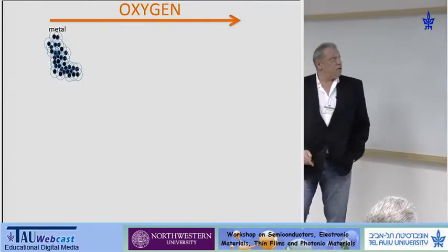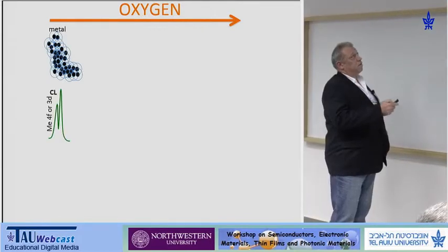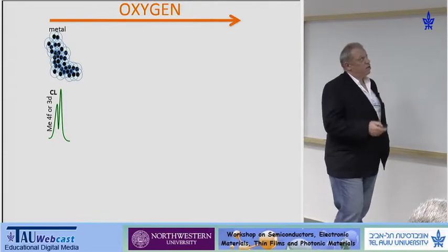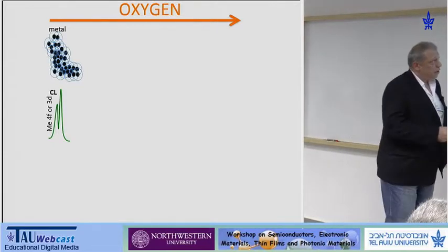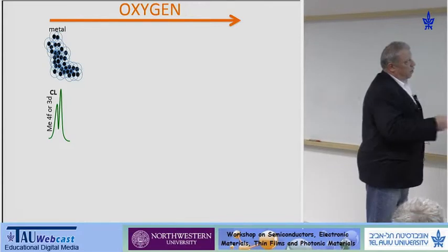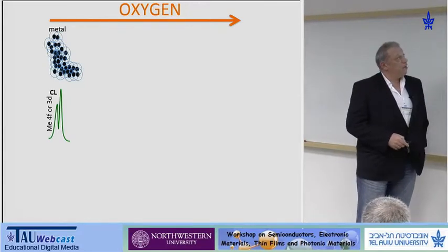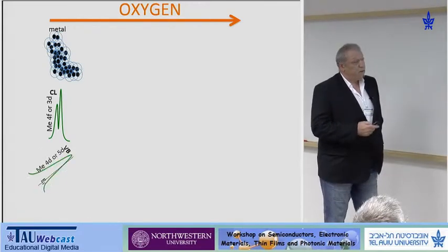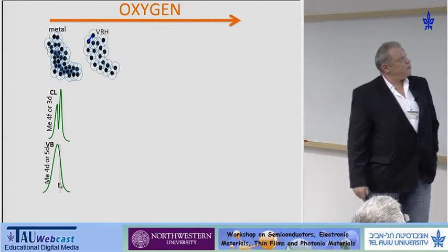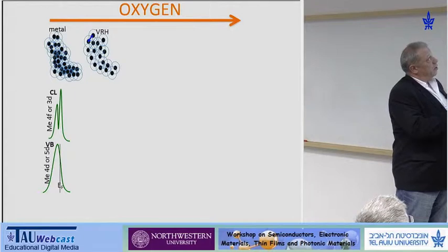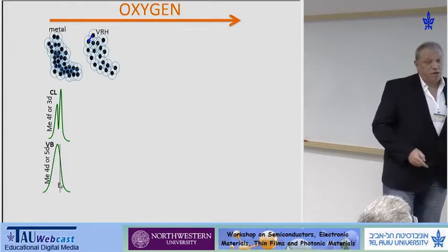All right, so what's the model? Very simple. Starting with the metal, we have very nice overlap of the wave functions. Localization is nowhere near. It is characterized by a very clear, single metallic doublet and the d band in the vicinity of the Fermi level. Then as we begin to oxidize, localization grows because the centers become more sparse.